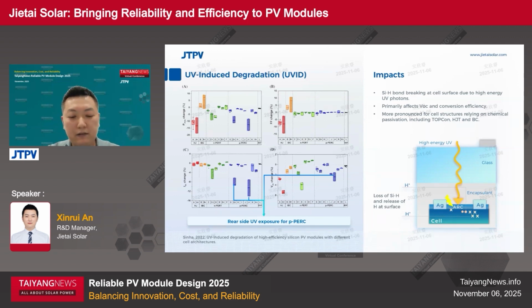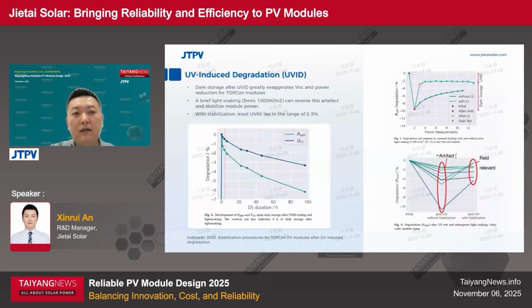And early reports reveal that for a variety of high-efficiency modules, including TOPCon, HJT, and BC, UVID loss can be as high as over 10% relative, and these cells usually have non or lightly diffused surfaces and rely more on the chemical passivation of dielectric layers. But such a high extent of UVID is, however, regarded as a combination of artifacts and real degradation, at least for TOPCon modules by Fraunhofer earlier this year.